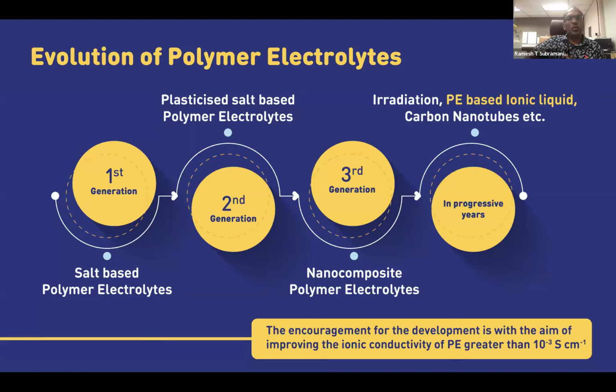Okay, here is the evolution of the polymer electrolyte. The reason we are using lithium is, if you look at the periodic table, after hydrogen and helium, lithium is the lightest. And when you use lithium salt-based polymer electrolytes, the conductivity can be increased to about 10 to the power of -5 Siemens per centimeter, but the conductivity is still not sufficient to be used for energy devices. That's where the second generation comes, which we call plasticized salt-based polymer electrolytes. When we use plasticizers, the conductivity increases. For those who are not familiar with plasticizing effect, it's something like adding water to clay to make things softer.